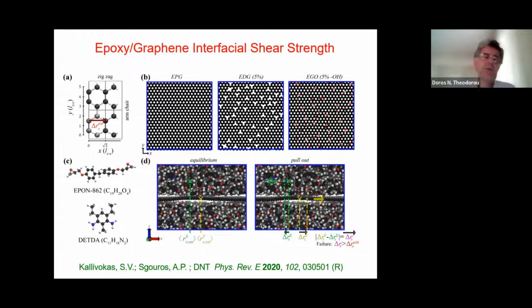More importantly, one can try to calculate mechanical properties for interfaces. So we tried to quantify the degree of mechanical cooperation that would be present between a polymer, in this case an epoxy resin, a glassy polymer of a rather complicated structure, and a nanofiller, in this case a graphene sheet. So we formed epoxy out of the monomer and the curing agent, the cross-linking agent. This is a very densely cross-linked glassy polymer. Of course, simulating the polymer itself is quite a long story because one has to essentially mimic the reactions whereby these networks are formed, but we managed to do so.